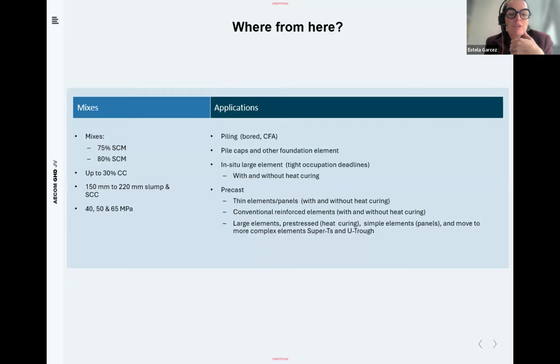Keep working on workability, work with the admixture suppliers, getting trials done to see how the finishing goes. But where we see things going is, yes, that it's possible to get those mixes with 75 to 80% SCM mixes that we already have in the market with other SCMs, but we believe it's quite possible to go further with the calcined clay. And in terms of applications, what we see for our program is we already know that bored piles, probably we can get those high SCMs. CFA piles for us is a critical element as well that we are trying to crack,